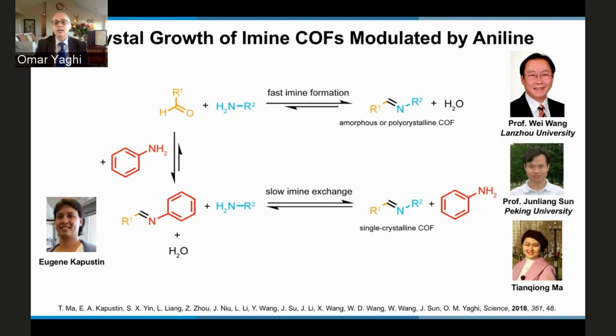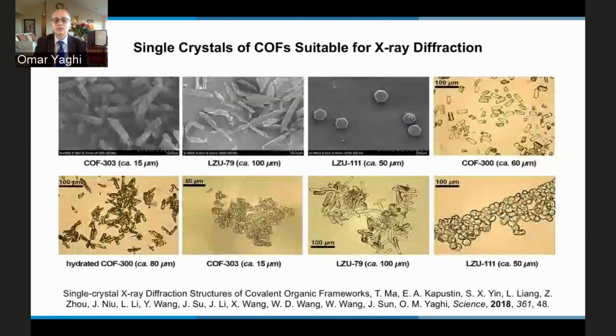Now, a lot of the structures that we have done in COFs over the years have been from powder diffraction. And very recently, we discovered a way of adding aniline, something BASF is very famous for, to control the imine exchange in the structure and therefore control the crystallinity. If you're patient and can wait many, many days, you can also get single crystals of COFs. These are shown here. As you see, as you increase the amount of aniline in that particular COF synthesis, so does the size of the crystal. So 100 micrometer crystals of covalently linked extended 2D and 3D structures are now possible.